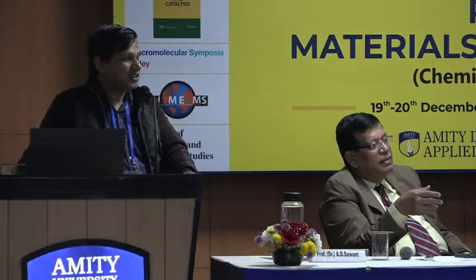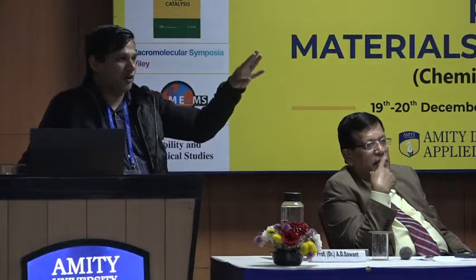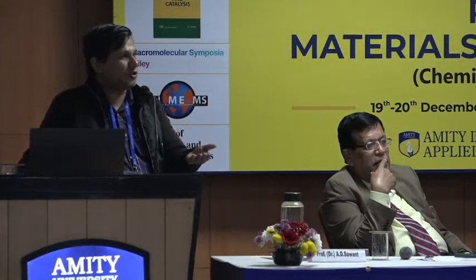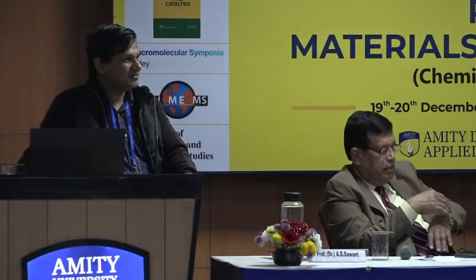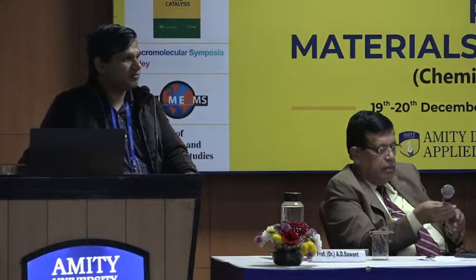Yes. I see your EDS data. I'm very surprised to see the data. What is the technique you use for the measurement? Is it SEM or FESEM, sorry? FESEM EDAX. If you measure any FESEM in the world, the oxygen itself comes in as air-conditional oxygen, so that cannot be eliminated. But in your case, you can see the carbon and the potassium only, but no oxygen. So is it a calibrated instrument? No, FESEM is a calibrated instrument, sir. We have a top-end machine. Oxygen is zero. The top-end machine has already taken care of all those things. And whenever we are measuring any material, we heat the material to remove the oxygen content. Impossible. If you are doing SEM, oxygen cannot be eliminated to zero.